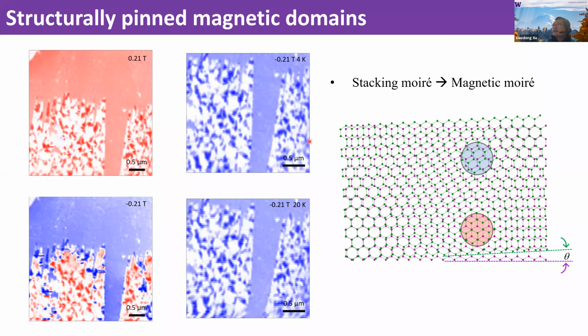For example, right here I show you, we measure at 4 Kelvin and at 20 Kelvin, and you can see the pattern looks exactly the same from top and bottom. We can also warm up the sample and cool down again, and the pattern won't change. So this just represents that the magnetic Moiré pattern is actually determined by the stacking Moiré.